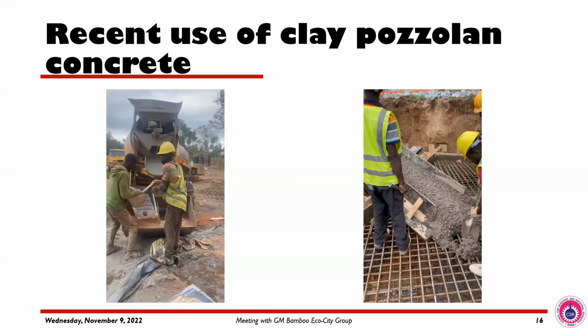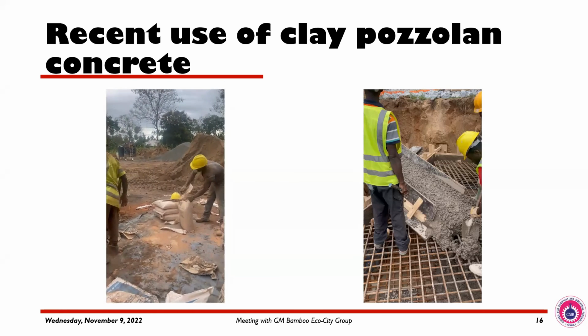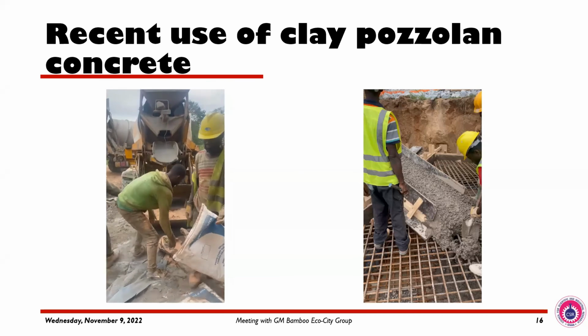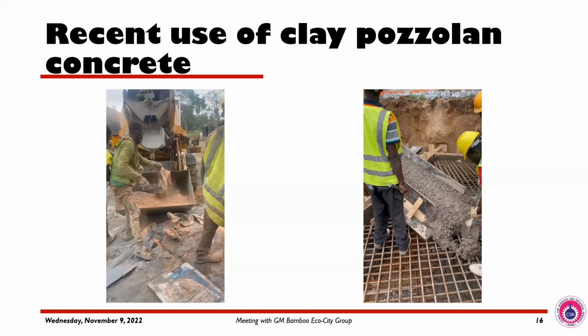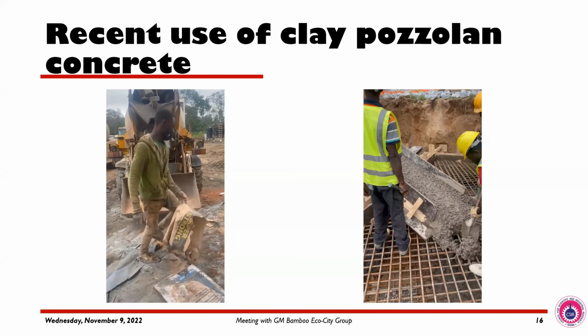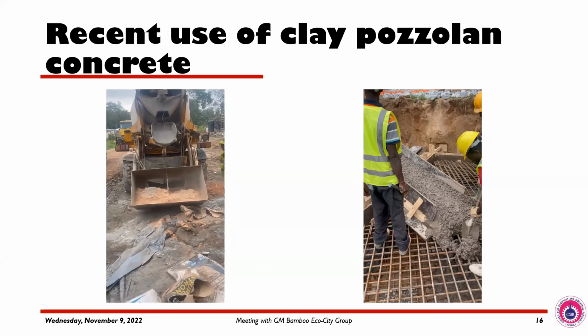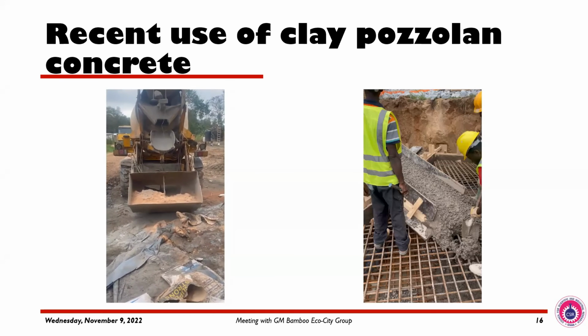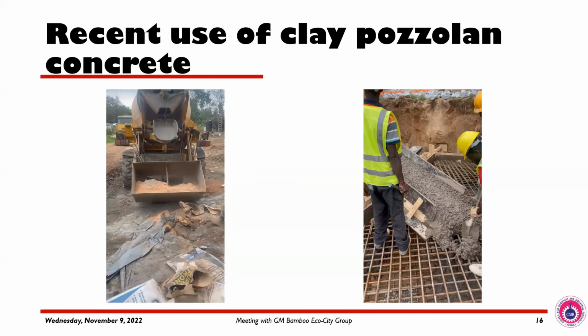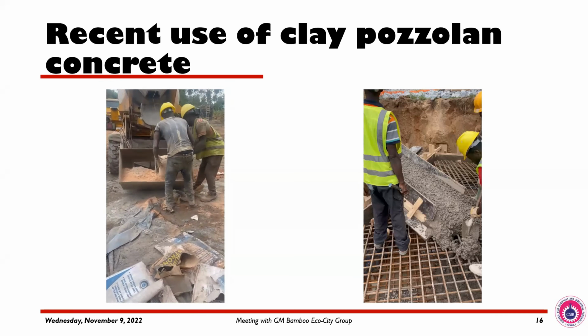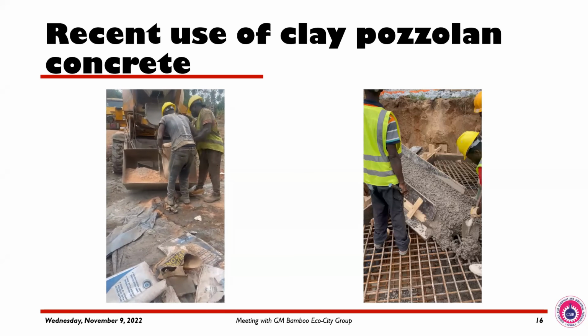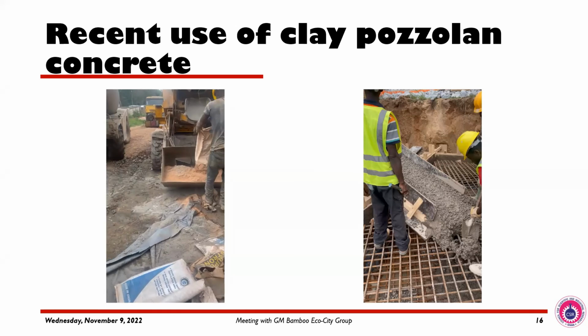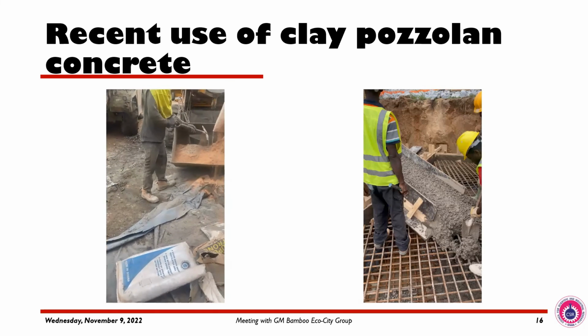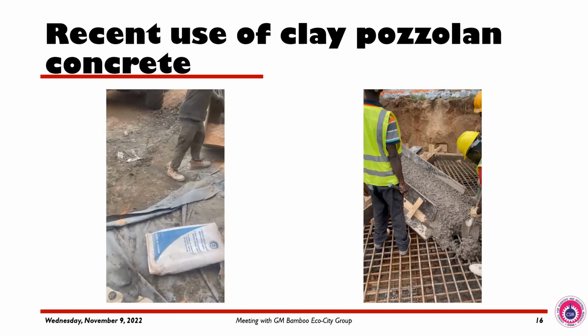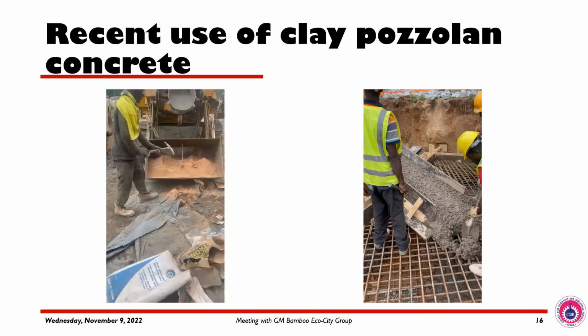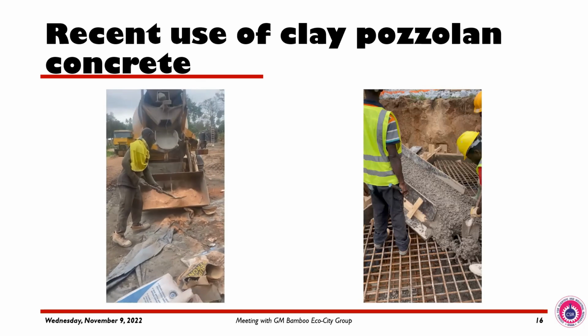So this is a concrete van. Make no mistake, we have done a concrete mix design already. So everything has been measured for the van, and the van is going to mix the concrete using the calcined clay pozzolana and the cement, and then they will produce the concrete. So this is a C30 concrete, but after we did this work, we were able to achieve about 38 megapascals. So we did it very well. We used a polycarboxylate superplasticizer, which can reduce water by 40%, and then we're there.